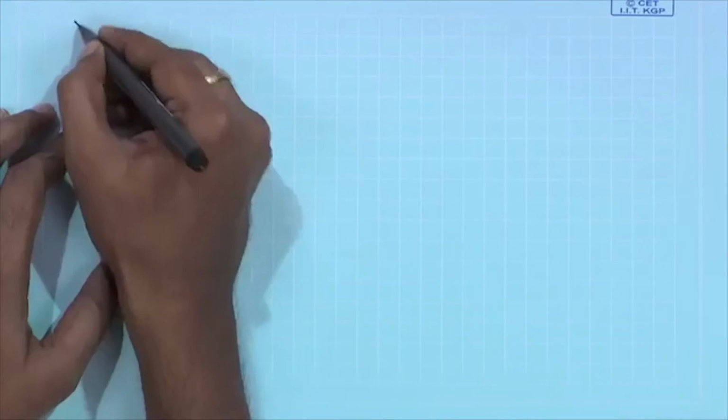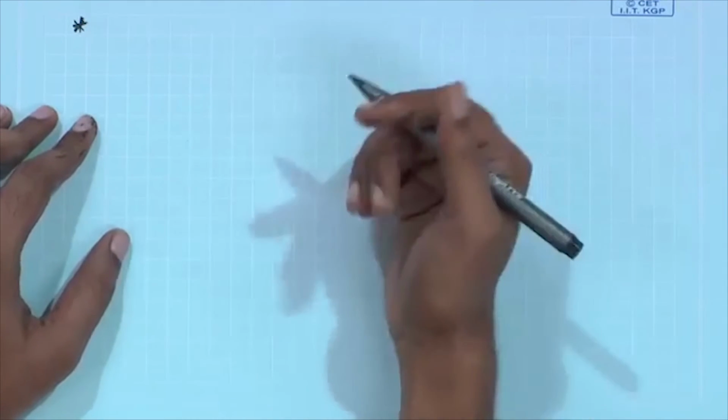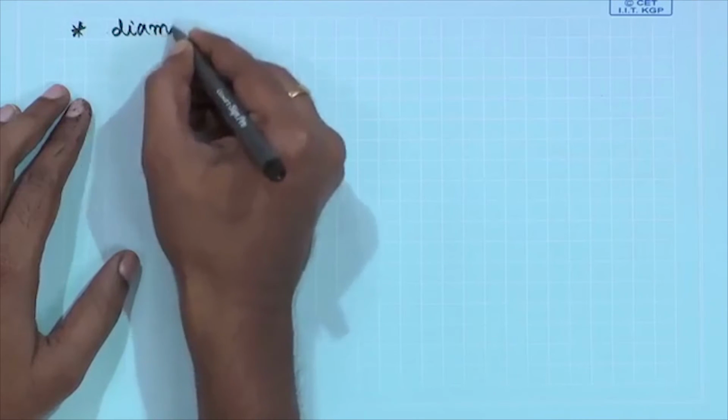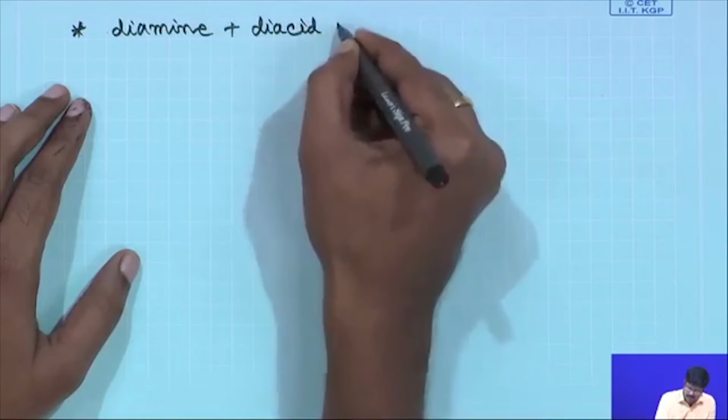The name suggests it, this polymerization works at the interface. Interface of what? Interface of two solvents. So, I will give you a generic example. So, typically the temperature is lower, 40-50 degrees Celsius or even lower than that, and the rate constant is quite high with respect to your normal reactions, because you are using acid chloride. And so, let us say you are reacting a diamine with a diacid chloride. So, you are making an amide,